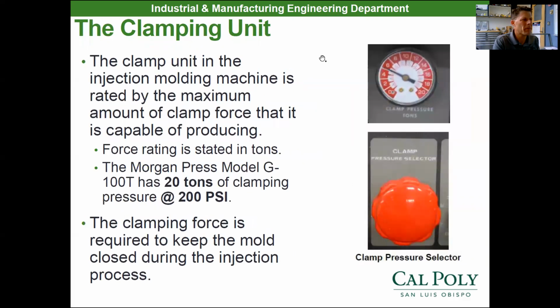So you have a little needle control valve down there that you twist, and that adjusts how much injection pressure we actually have. Now, the clamping unit is rated. The clamping unit is how much force the machine is putting on the two mold halves in order to keep them together. Our machine is capable of 20 tons at 200 PSI. We don't have 200 PSI of shop air. We have about 120 PSI, so we can't actually clamp 20 tons of pressure. We can get about 12 tons of pressure out of our machine.